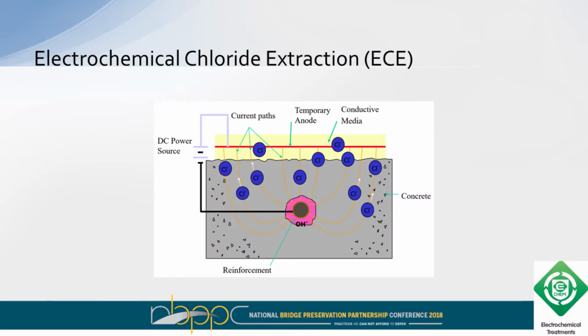Electrochemical chloride extraction is similar to impressed current, except it's a temporary treatment, so you're putting a lot of current, similar like we just showed with impressed current systems, to the steel, but only for a short duration. So the idea is to passivate the steel. This is an example, and you see this used commonly on historic structures because it's a treatment that you can do. You can passivate the steel, pull the system off, and not really change the appearance of the structure too much.